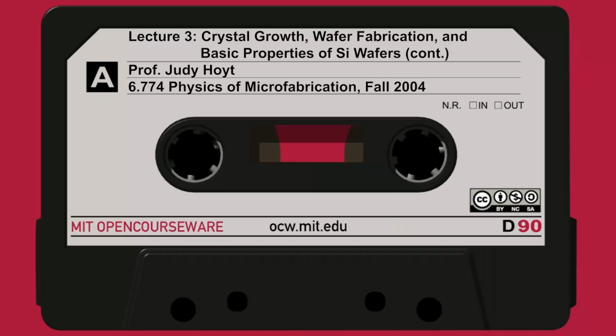So another thing to realize, this is kind of obvious, but sometimes we forget it, is that as the doping changes, as I dope the crystal more heavily, let's say, and therefore the Fermi level changes, not only do I change the charge states, but the total number of vacancies changes. It's not just that I'm taking a certain fixed number and changing how they're charged. So thinking about it this way, this is the expression we wrote here, this equation, for the neutral vacancy population. It's only a function of temperature, not doping, or not the Fermi level. So that's very simple. It's just an exponential dependence on temperature.